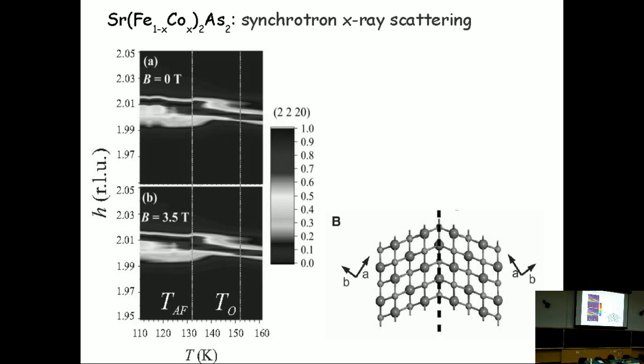which are overlapped. And this overlapping happens because it's not so clear, the orthorhombic distortion here, because with this cobalt doping, you can't be completely homogeneous. There are some fluctuations in the doping, and that changes a little bit the lattice parameters of parts of the sample. So we have the broadening of the Bragg peaks not only in the orthorhombic phase but also in the tetragonal phase. So it's more difficult to study in detail the structure for this kind of doped systems, but we clearly see that there is a transition going on here.